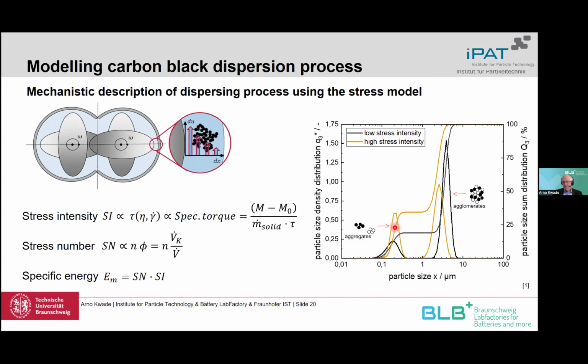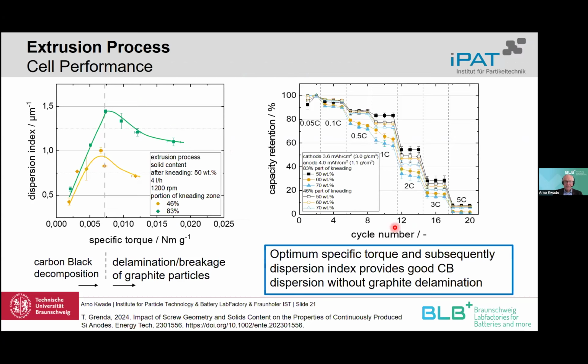Now, going to the next slide, we can show that if we also increase the concentration of our particles, that means we have a very high viscosity within the extrusion, and we normally have some kneading blocks installed in the extruder, then you can see that the dispersion index increases a lot. And we have a really high torque, which then decreases again. The decrease is due especially to the delamination of the graphite particles. So we have a degradation, which we don't want to see. We can also have this with smaller concentration, but it's really only a little bit.